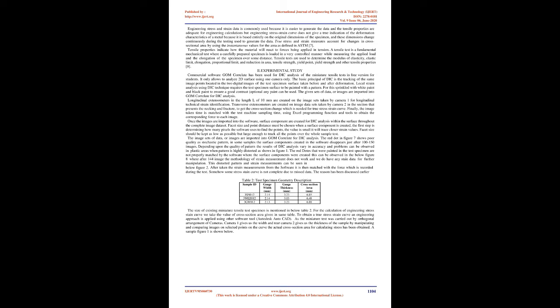4. The 2 major ways of increasing yield strength of steel are alloying elements or using heat treatment. Keep in mind that alloying elements in some cases also worsen the fabrication properties of steel, especially the welding ability. On the contrary, heat treatment has a major advantage on the microscopic crystalline structure of the material and results in a fine-grained steel with higher strength and toughness. 5. Table 1 shows all the types of available steel grades according to Eurocode 2007, and all these materials are now in practice in European construction for steel structures.